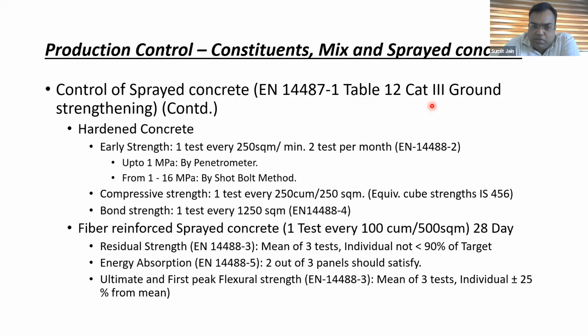Now we come to the fiber reinforced sprayed concrete. Here we are testing one test every 100 cubic meters or 500 square meters, and the tests are performed when the age is 28 days. In 28 days, 3 tests are performed: residual strength, energy absorption strength, and the ultimate and first peak flexural strength. There is a certain criteria to be met for residual strength, like the mean value of 3 tests, and the individual test limit should meet 90% of the target strength.